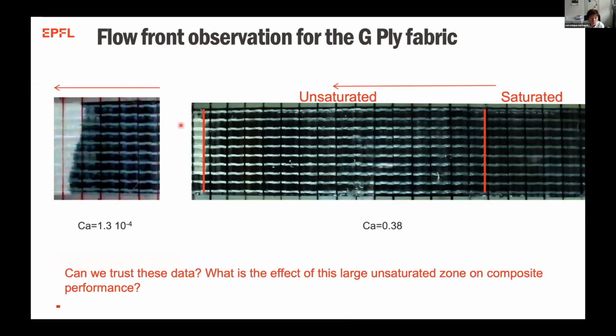And if you look at the flow front, if you go slowly, you have a more or less equilibrated flow front. If you go super fast, you have a very large unsaturated flow. You see here, those bundles are just not at all impregnated. They are completely dry along a super long region, whereas the liquid has gone into the channels.